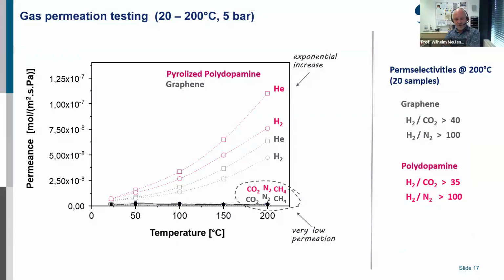So regarding the temperature range where these membranes are applicable, we made also a test between room temperature and 200 degrees C. And what we can observe here is that at low temperatures, in principle, we do not have a good separation factor. But by increasing the temperature, we guess that also the distance between the layers or the rings increases, and then we have some flux of helium and hydrogen, but still a very low amount of flux of CO2, nitrogen, and CH4. So we were able to reach separation factors between 40 and 100 between the different gases.